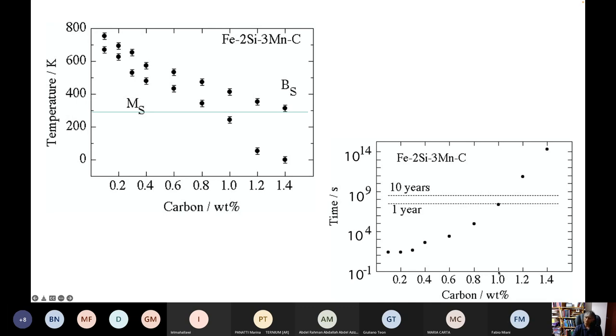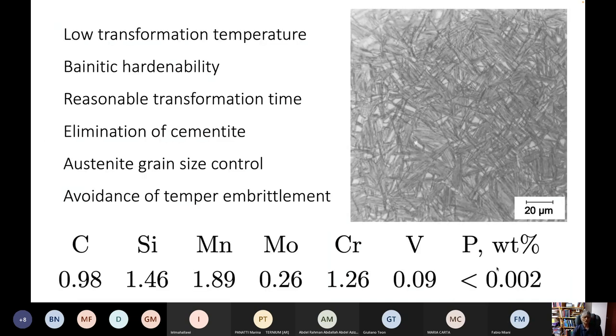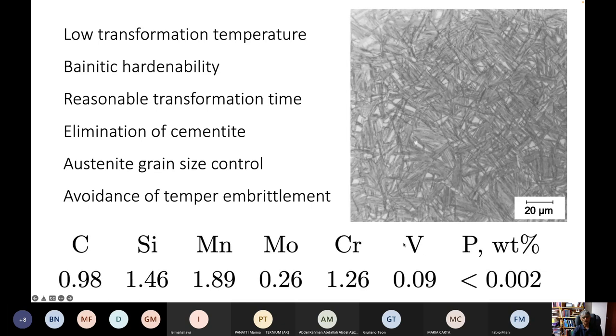So we designed an alloy containing about one weight percent carbon, which should take roughly 10 days for the transformation to complete. It's a very simple alloy: one weight percent carbon, silicon to stop carbide formation, some hardenability, and molybdenum to pin down phosphorus atoms and therefore stop embrittlement — something you need to be careful about when dealing with strong steels. Strong steels are very susceptible to embrittlement at the austenite grain boundaries by elements like phosphorus. We predict that if we transform at 200 degrees centigrade, this should take about 10 days. We have manganese and chromium for hardenability, silicon for eliminating the cementite, a small amount of vanadium to prevent coarse austenite grain size, and molybdenum to pin down the phosphorus.